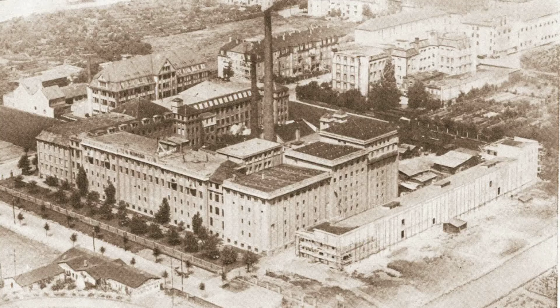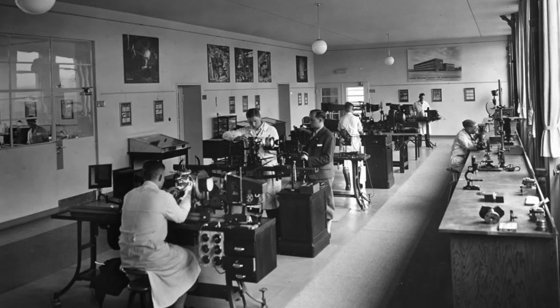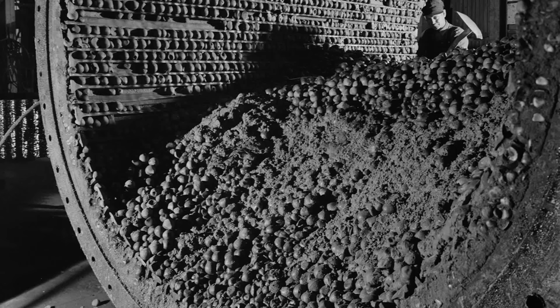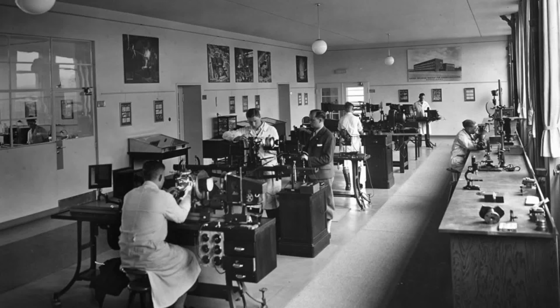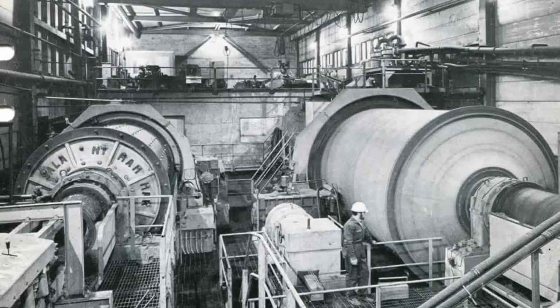At the Osram Research Organization in Germany, Karl Schröter and his colleagues were investigating better materials for drawing tungsten filament wire. They experimented with tungsten carbide powders and different metallic binders. Iron was tried, nickel was tried, then cobalt. The result with cobalt was different. Instead of trying to make a tool from one homogeneous metal, the researchers were effectively creating a composite. Microscopic particles of tungsten carbide supplied the hardness. Cobalt formed a metallic binder around them, holding the hard particles together and giving the finished material enough toughness to become useful.